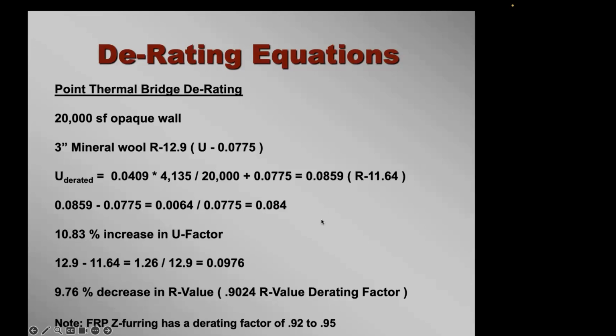So you take the U derated less the U opaque, there's your difference, divided by the U opaque. So the difference is an add of 0.084, which is a 10.83% increase in the U factor. If you want to do the devaluing of the R value, you take your original 12.9 minus the 11.64 derated. The difference is 1.26 divided by the original 12.9 is 0.0976, so it's a 9.76% decrease. So your derating value is 0.9.